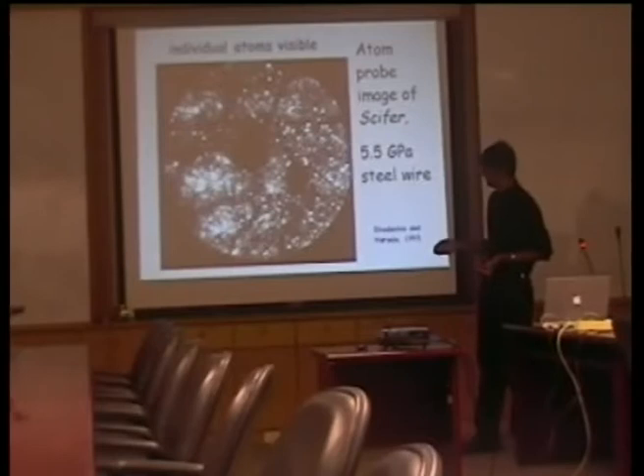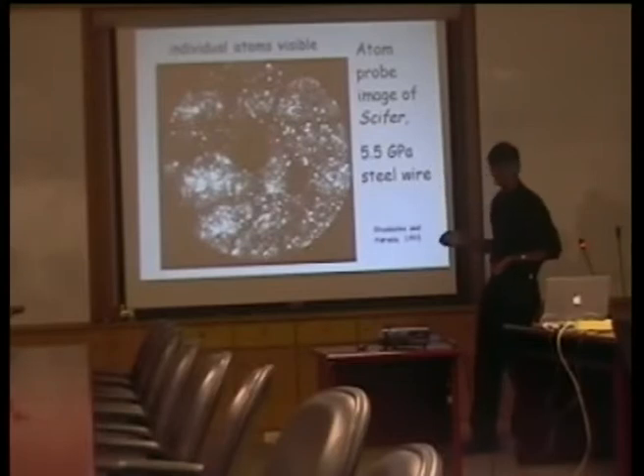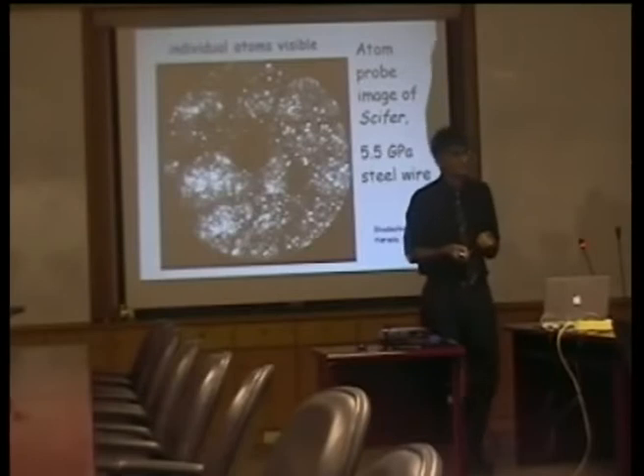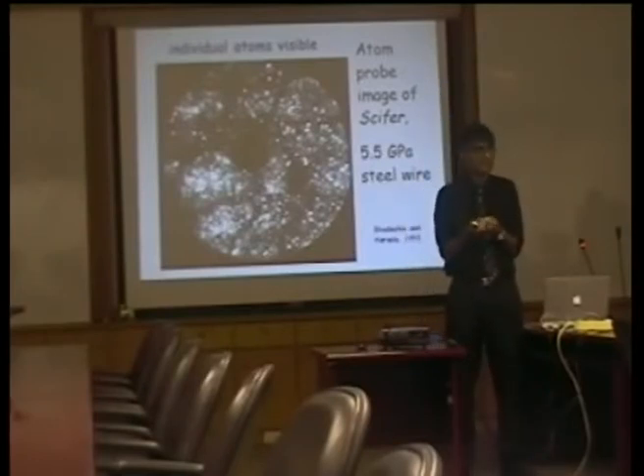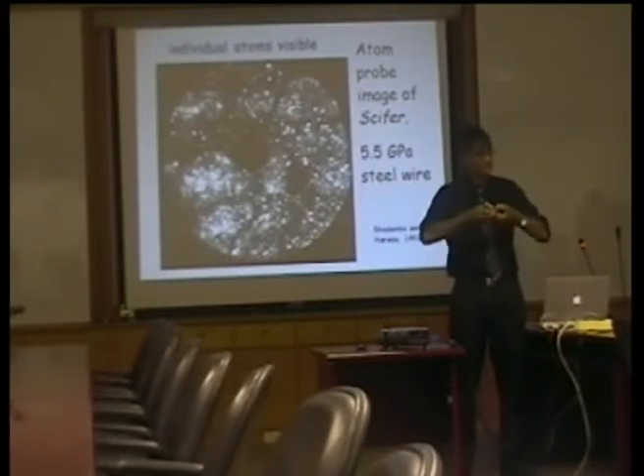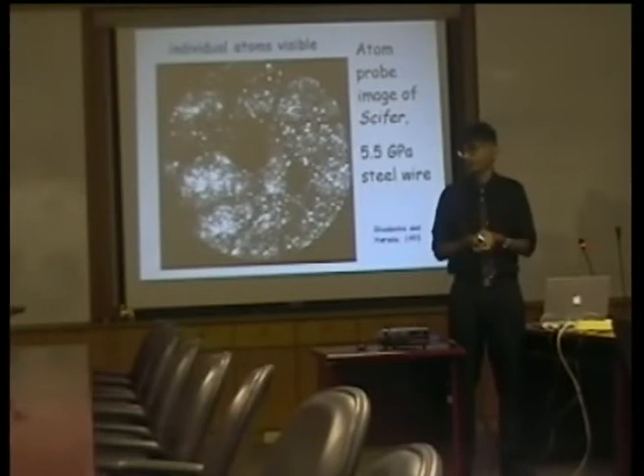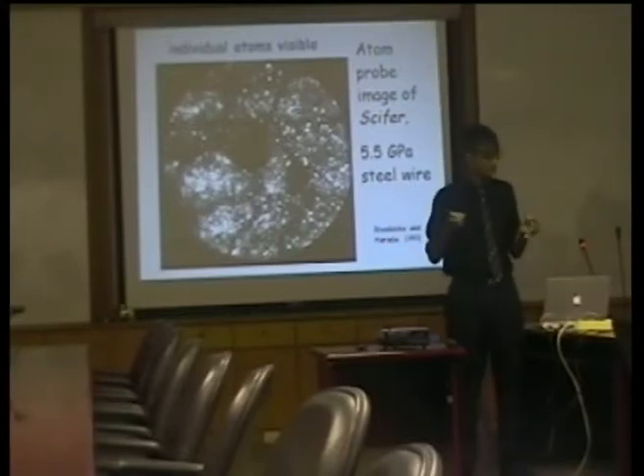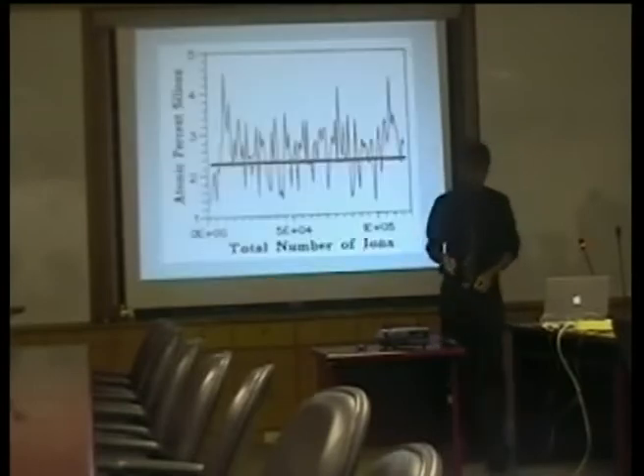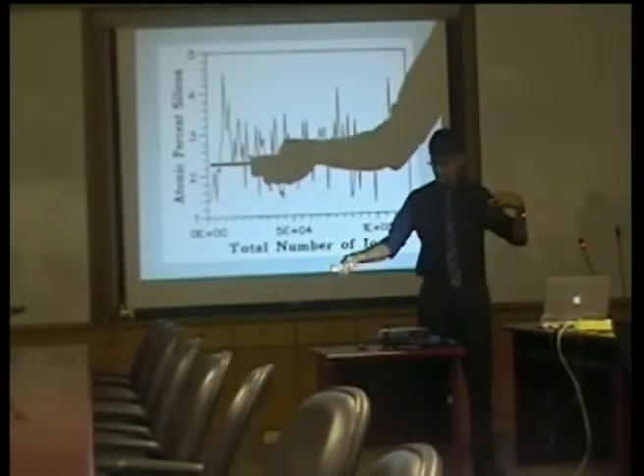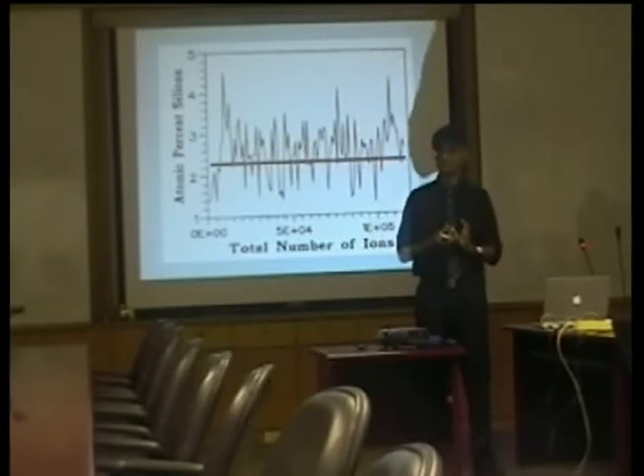The thing that I want you to notice, which is very interesting, is that look, there are these dark regions here. You see some dark boundaries where it's difficult to see the atoms. Those boundaries, dark regions are actually interfaces. What we've done by severe deformation is we've reduced the size of the crystal to something like 5 to 10 nanometers. By having this huge deformation, the grain size has decreased enormously. Furthermore, we had this region of high carbon martensite and low carbon ferrite. The severe deformation mixes up those two phases.